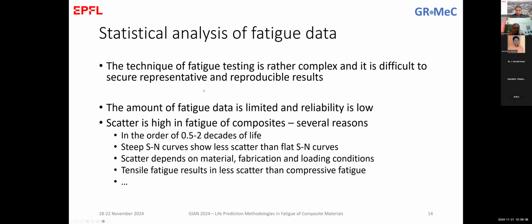So we've seen again statistical analysis tools. The discussion that we are doing about scatter is what we've seen here. Between half and 2 decades of life, people believe that this is a reasonable scatter. I would say for me it's more or less 1 decade of life with the experience that we have now with composites. And this scatter is depending on the material and the fabrication. You've seen yesterday these adhesives and the different ways that we use to fabricate.